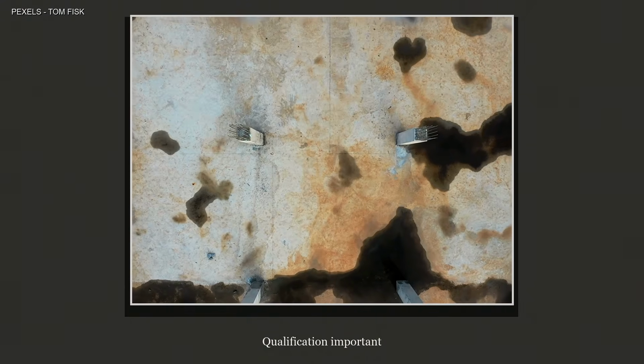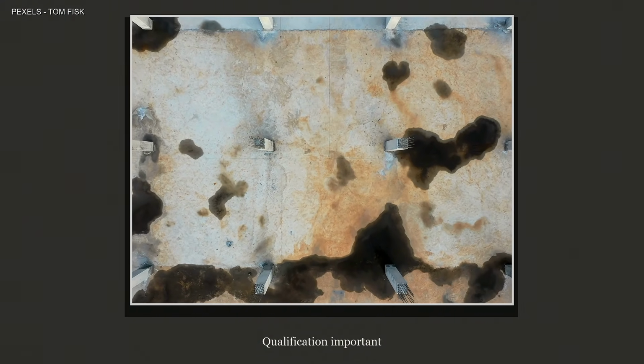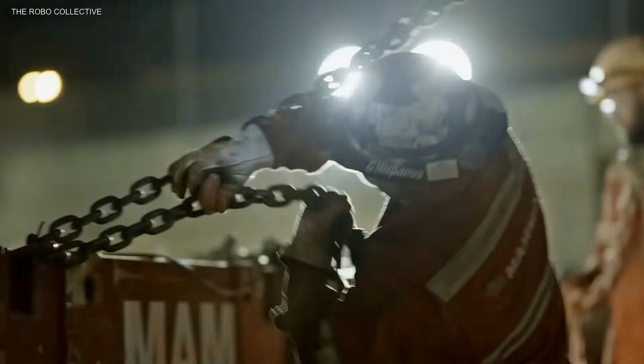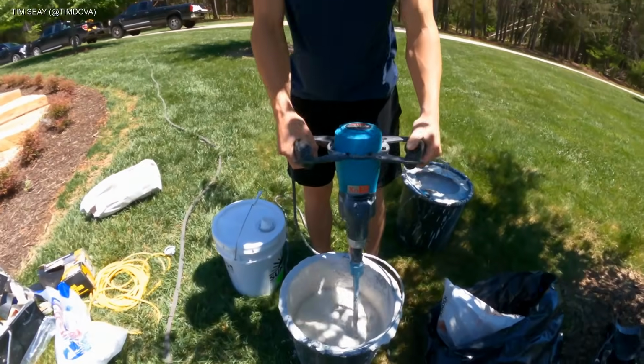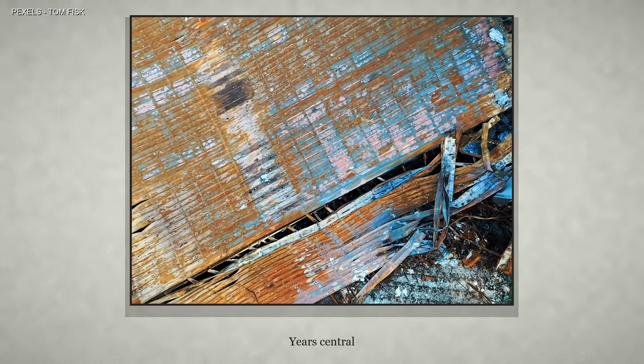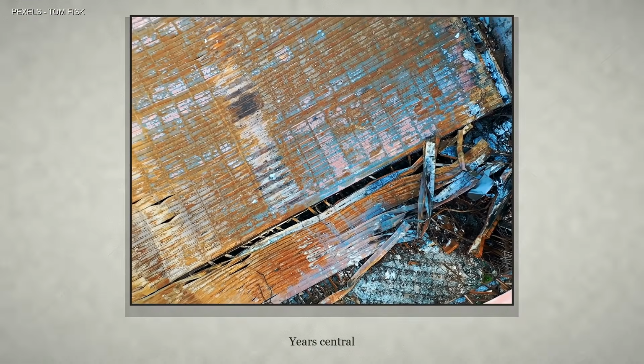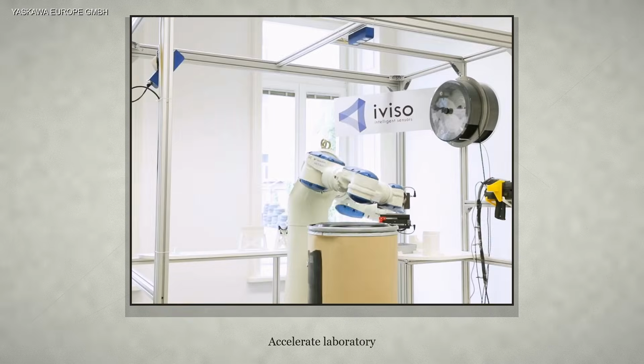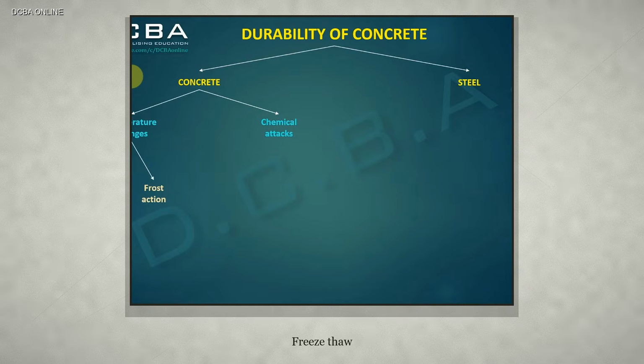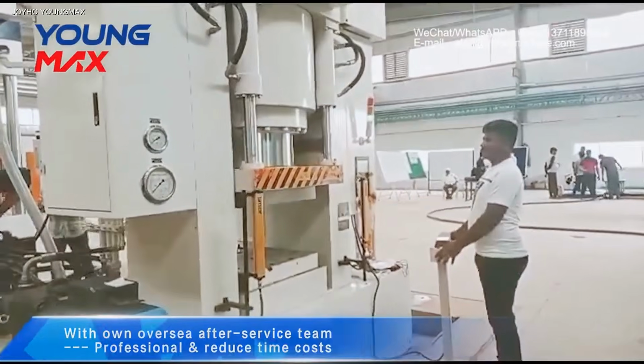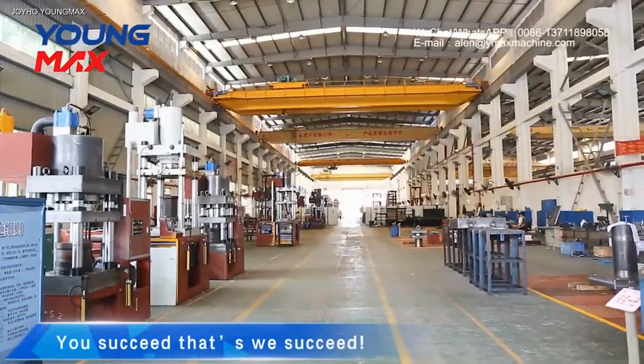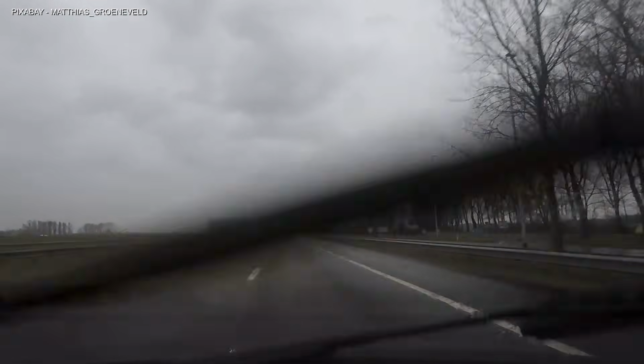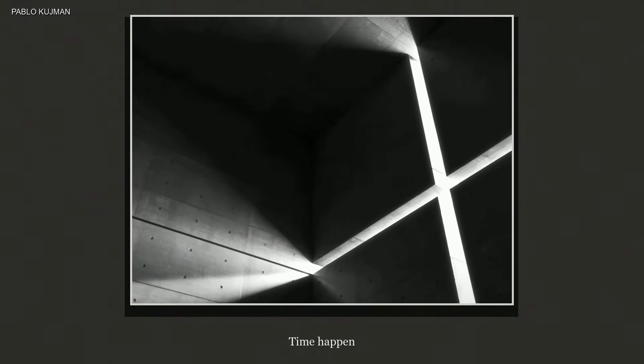That qualification is important. This material has not been sitting under American bridges for 50 years. C-Crete's oldest commercial pour is only a little more than 3 years old. The company says it shows no visible degradation or cracking. Good. But 3 years is not 50. That is one of the central problems every new construction material faces. You can accelerate laboratory tests. You can expose samples to freeze-thaw cycling. You can measure chloride penetration. You can test shrinkage. But there is no machine that can instantly give you 4 decades of real weather, workmanship, maintenance, and abuse. Time has to happen.